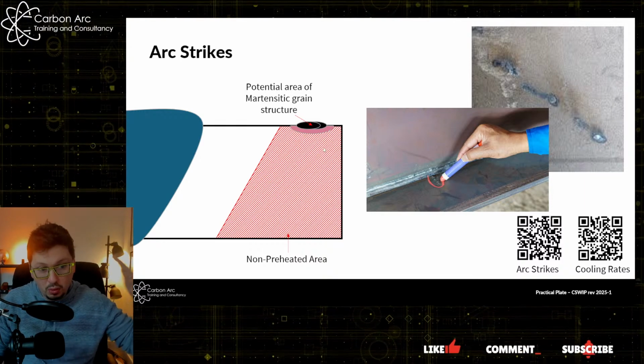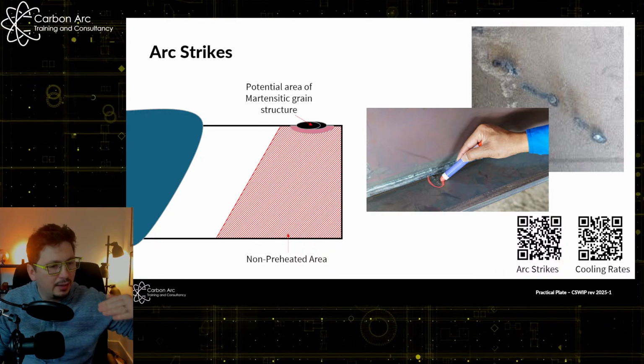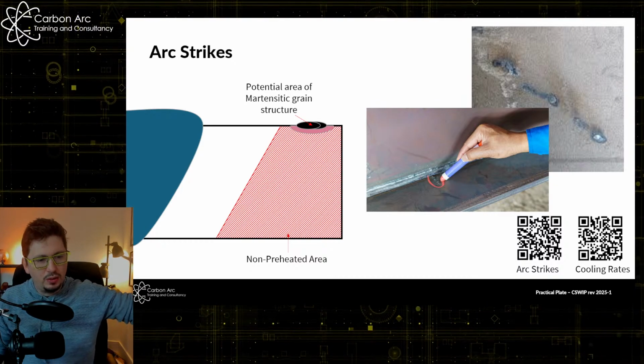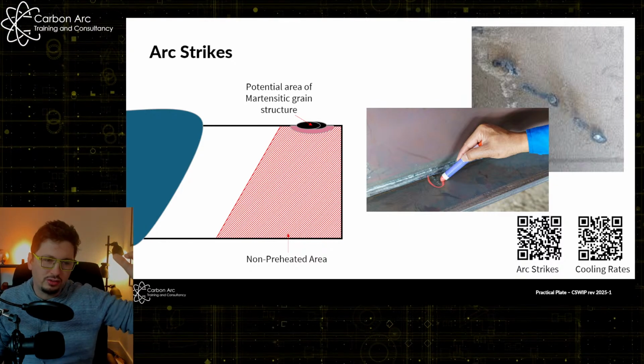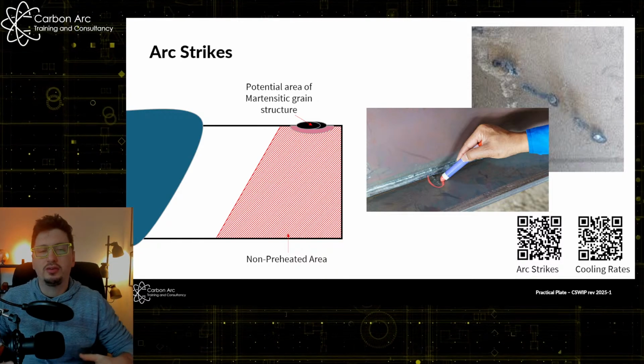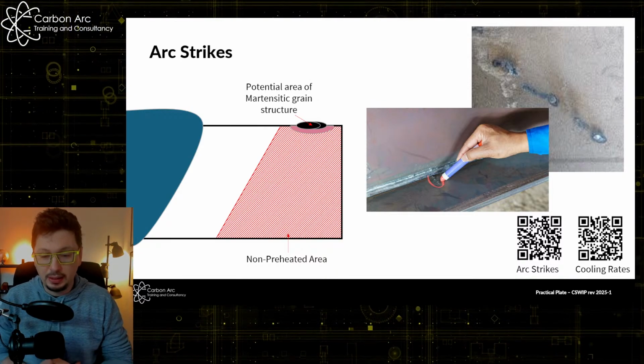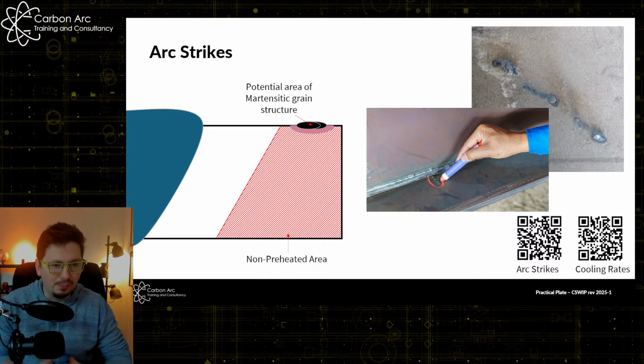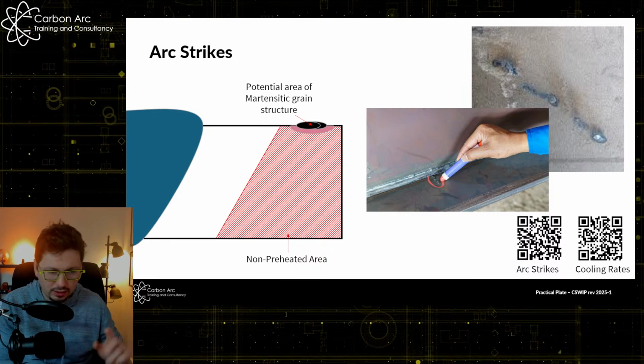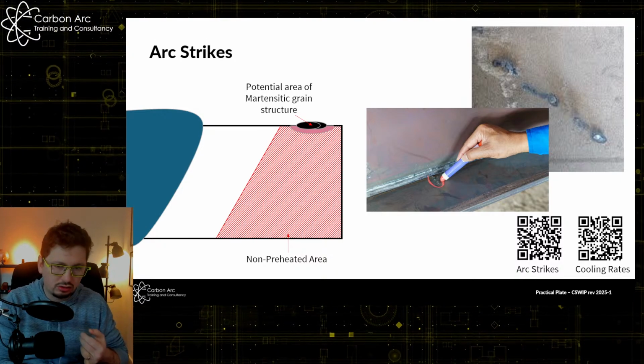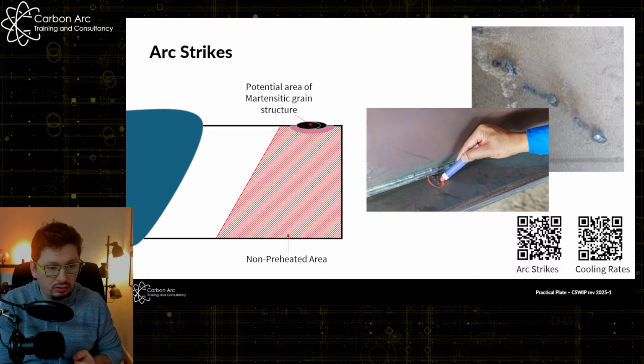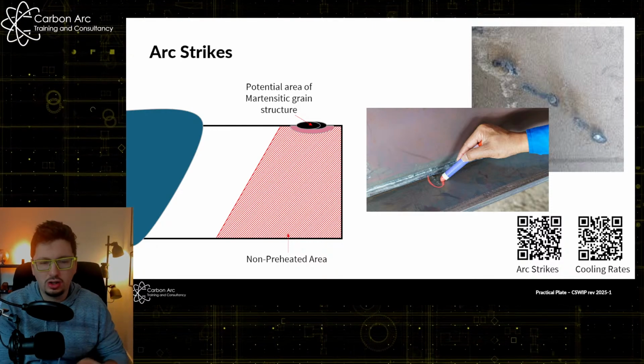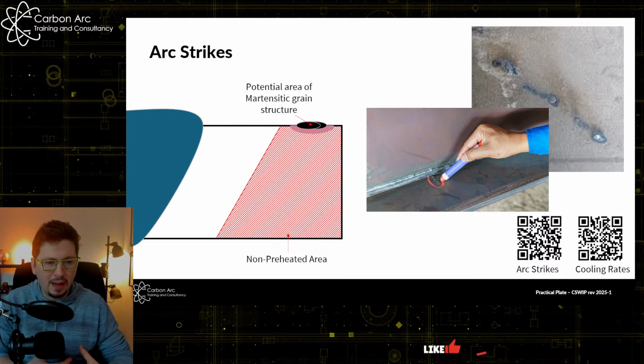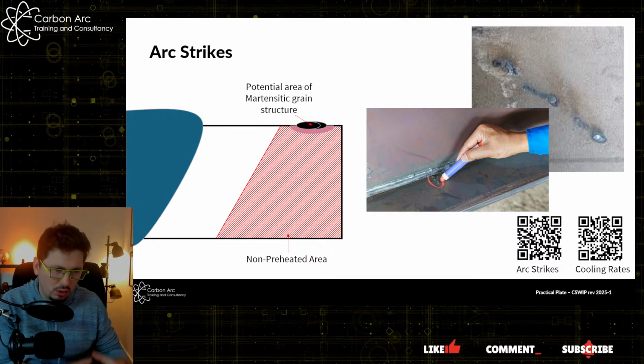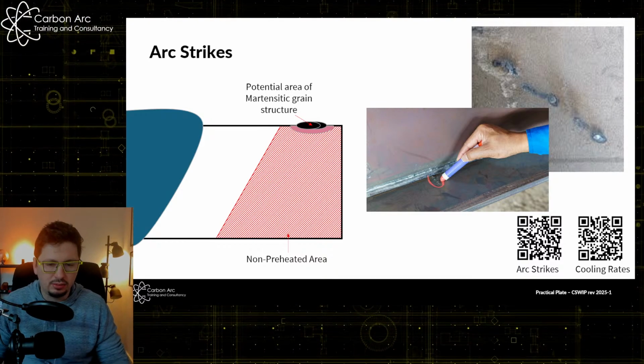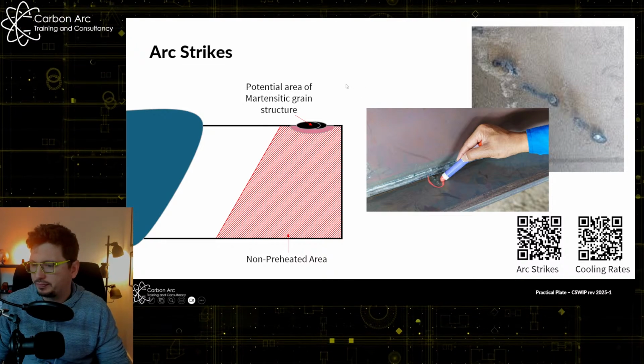This is where we are heating the material up quite rapidly from cold, so we get above its transition temperature. We change it all up to liquid and then to austenite and fast cool it. So now it has a much higher chance of being a martensitic structure, which is more likely to break. Okay, again, we've got videos on arc strikes, identification, and cooling rates on the channel. Give that a look. Okay, we're generally going to bang these out in areas. So you see one area, 2 areas, 3 areas, whatever that may be.